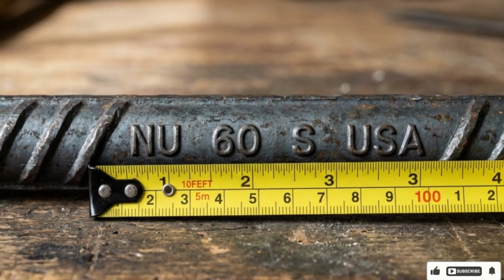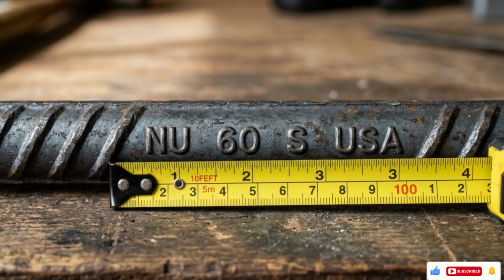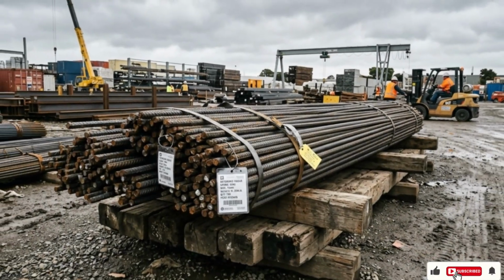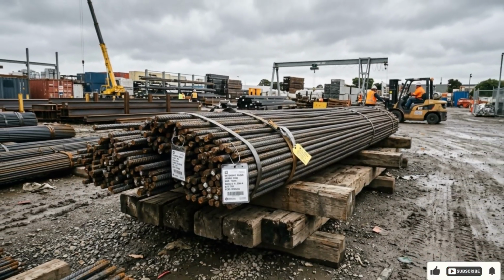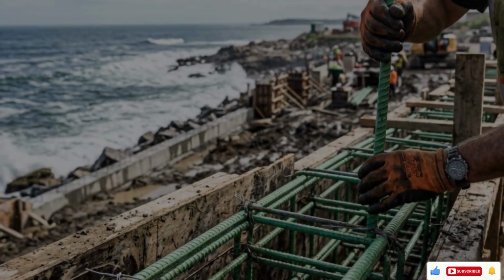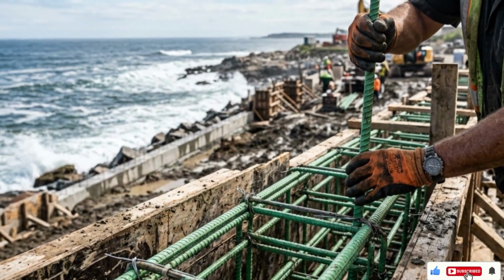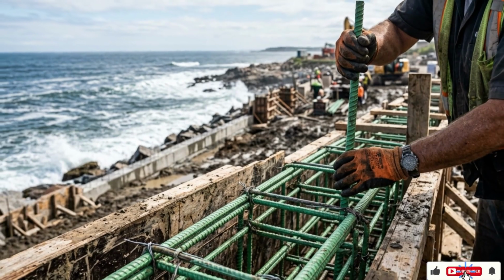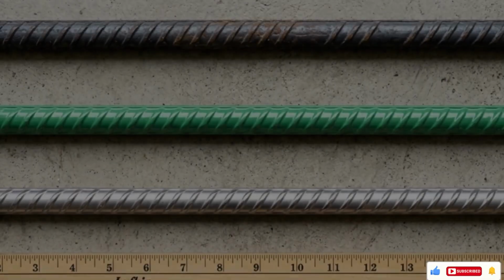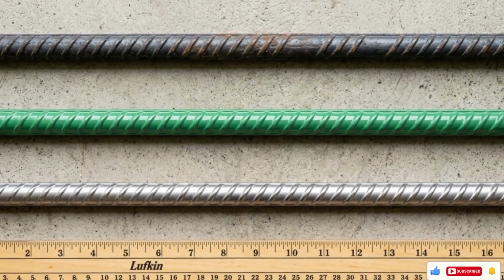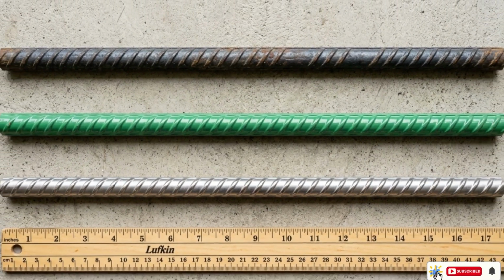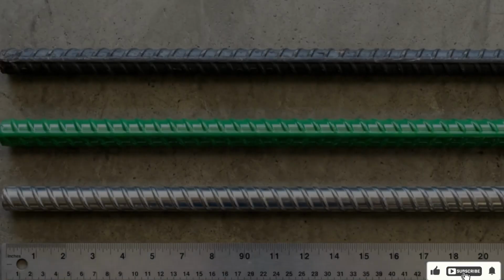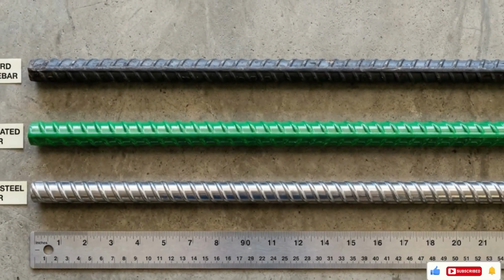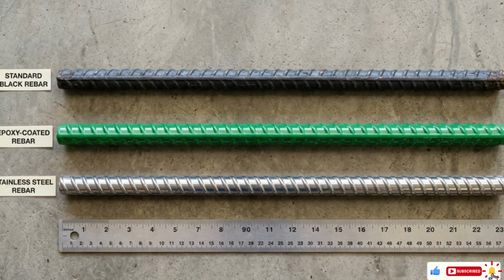Reinforcing steel. Grade 60 deformed rebar, yield strength 420 megapascals, is the standard for residential foundations globally. In coastal environments or areas with high chloride exposure, specify epoxy-coated rebar at a 20 to 30% cost premium over standard bar. In highly corrosive industrial environments, stainless steel rebar may be specified. The bar must be cleaned, free of loose rust, mud, oil, or paint, at the time of concrete placement, as these contaminants reduce the bond between steel and concrete.